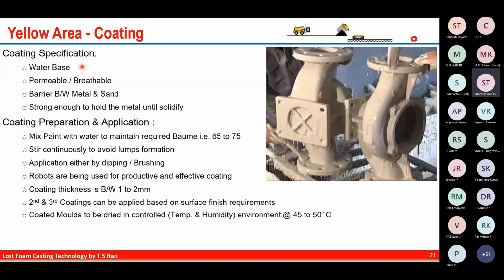Application can be done by dipping or by brushing, or I have even seen robots. Robots are used for dipping the foams into the paint. And coating thickness normally varies between 1 to 2 millimeters, depending on the surface finish requirement of the casting.